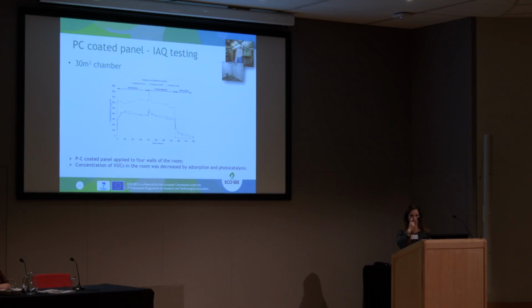And then the last experiment is a combination between adsorption in the dark and photocatalysis. So what I did, I turned off the lights inside of the chamber and covered the windows, so I made sure that the inside of the chamber was in complete dark conditions. And then I ran the test for 1 week, and then I turned on the light to start the photocatalysis, and then observed the uptake of VOCs in both phases.